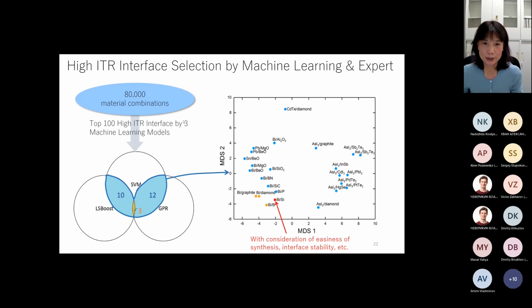So actually, we try to predict the ITR for the 80,000 material combinations, and each model recommends the top 100 high-ITR interfaces. And we can see that only 3 of the interfaces are recommended by all of these 3 methods. And another 22 interfaces are recommended by 2 models. Since we would like to have different points of view, we take this overlap part, and this is the multi-dimensional scaling of these 25 interfaces. The orange ones are the three interfaces recommended by all three models.